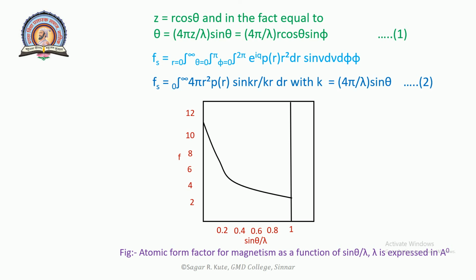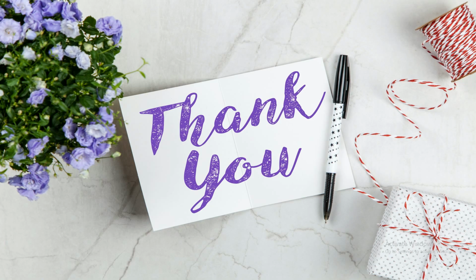The charge distribution on which such curves are based may be obtained, as an approximation for atoms with a large number of electrons, from the statistical atomic model developed by Thomas and Fermi. In some cases, for solids with simple structure, the atomic scattering factor may be determined experimentally from the intensity measurements. The agreement with the theoretical curve is generally good. Now this was the structure of atomic form factor, or atomic scattering factor. Thank you so much.